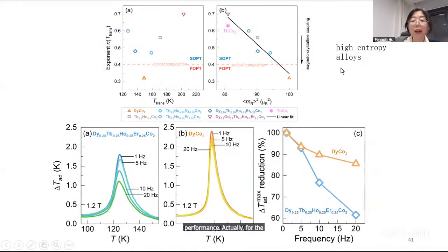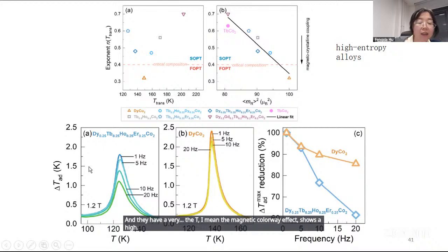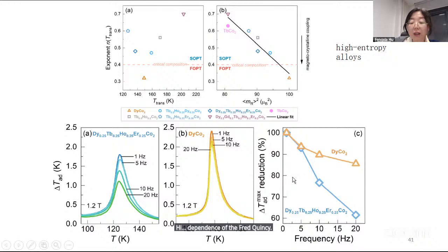Actually, for the high entropy alloys, I mean this composition, the transition is second order in nature, and this one, DyCo2, is first order. Also, this one shows the second order transition, and the delta T, I mean the magnetocaloric effect, shows a high dependence on the frequency. At the low frequency, lower than 5 hertz, the dependence on the frequency is similar, I mean this one and this one. But at the high frequency, the delta T goes down sharply. The reason is the introduced lattice distortion.